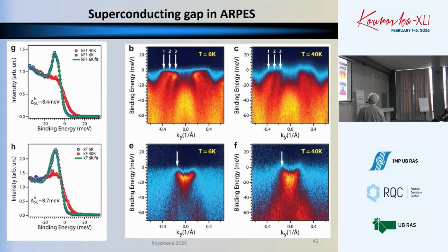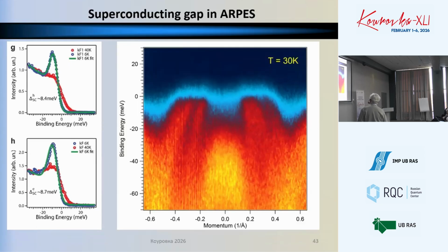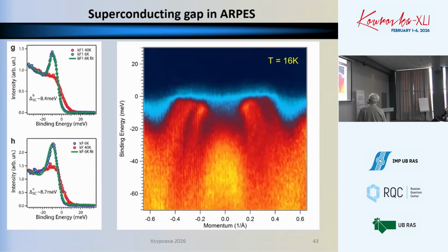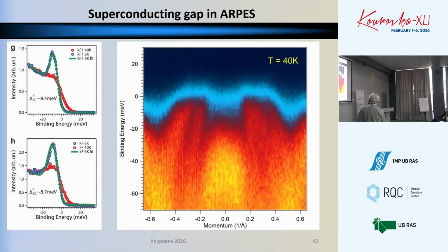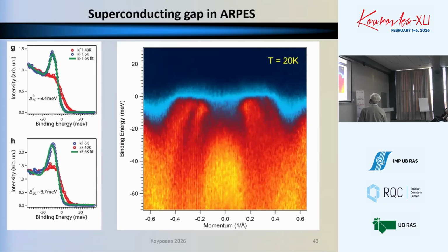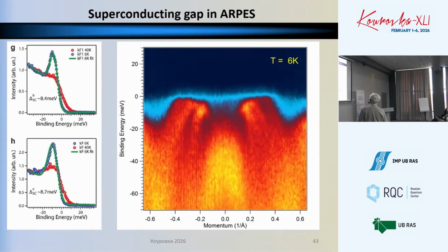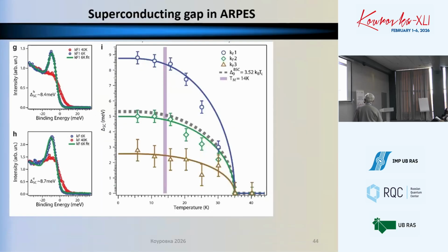Nevertheless, this is a typical profile of the energy spectrum when you go along one of these white arrows. So electrons which are sitting here in the gap are relocated as soon as the superconducting gap opens. And this is a typical superconducting behavior. You see here in the movie how the electrons redistribute when the superconductivity starts. So 40 Kelvin is above the superconducting temperature, and 6 Kelvin is deep in the superconducting state. Now, we applied a lot of effort trying to find the effect of the magnetic ordering on the superconductivity, but in ARPES we didn't see anything.